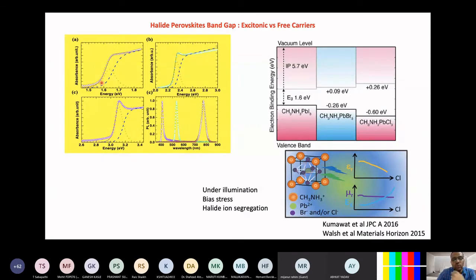We could basically use the 1960s Elliott theory model. Elliott is the one who basically proposed the excitons model. So we have the Frenkel excitons and we have the Mott excitons. The Frenkel excitons are the molecular excitons. They are very small in size, whereas the Wannier-Mott excitons are very large in size, which are available in inorganic semiconductors, and that's what happens here as well. So we could separately determine the electronic band gap by separating out the excitonic contribution from the UV spectrum.